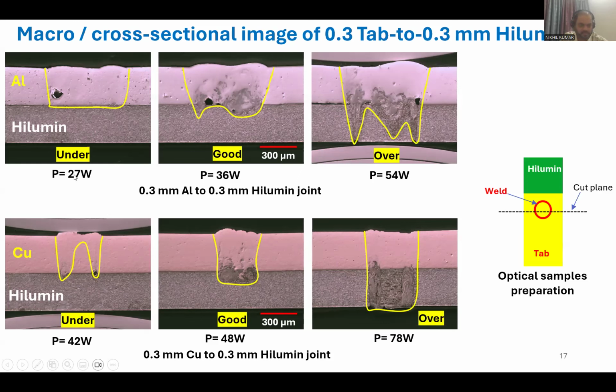And this is an example for copper to Hilumin. So this also, you can see there is hardly any penetration on the bottom sheet. This can be considered as underweld. This is good weld and this is overweld, because we have fully penetrated the bottom sheet. So this is like identification for you. How would you identify which is good, bad, and overweld?